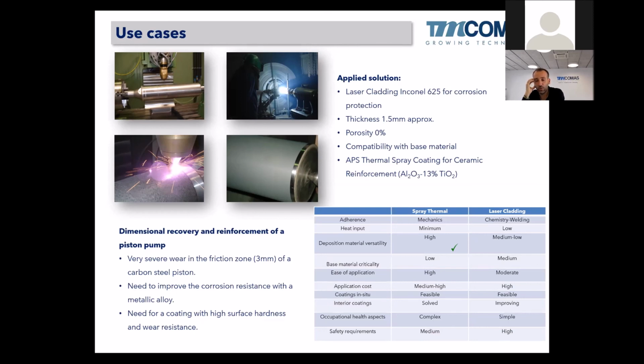So at the end we had a base layer of Inconel 625 to protect the carbon steel piston against corrosion damage. And on top of the Inconel 625, we had a ceramic thermal spray coating. We chose a ceramic because it has a high wear resistance. It is not as expensive as tungsten carbide, and it's enough for this application.